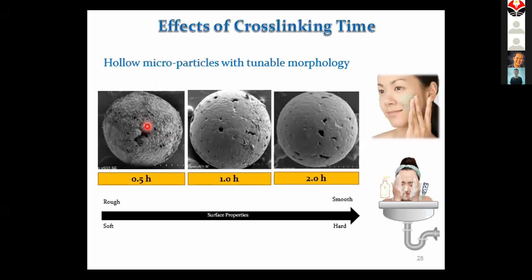...a crystalline domain of the polymer. If we have less cross-linking, we have more crystal, so we have a rough surface. However, if we cross-link the polymer for longer and longer time, we have more cross-linked structure, meaning less crystal. So we do not have the pattern like this anymore - the morphology here is very smooth. We can use this as a scrub bead in cosmetic applications.